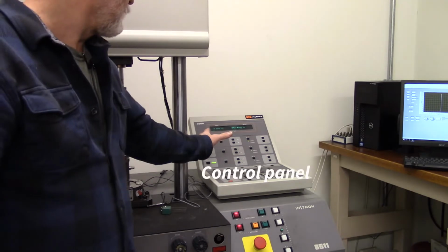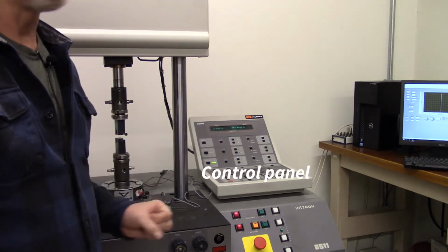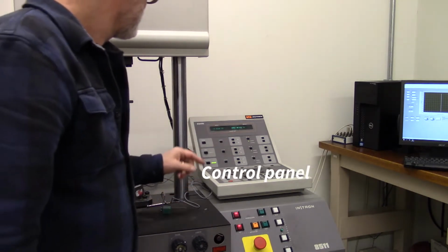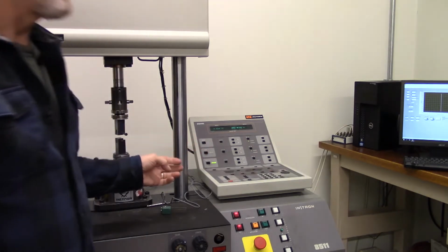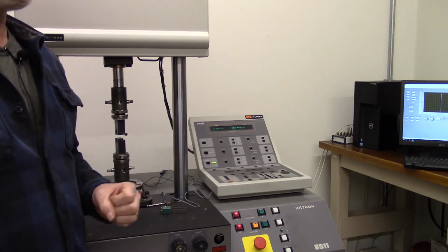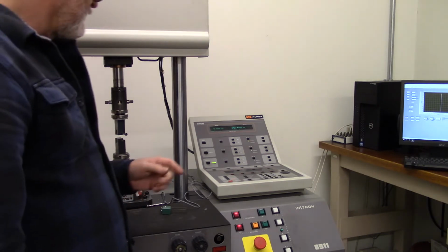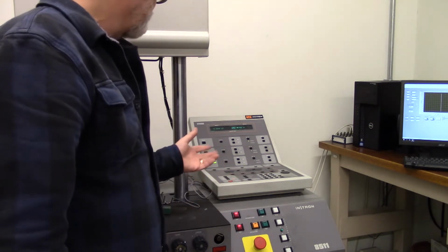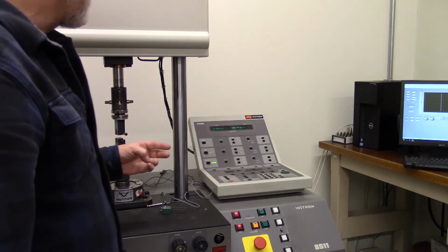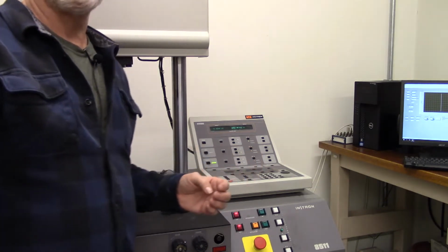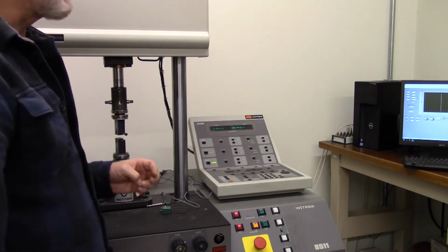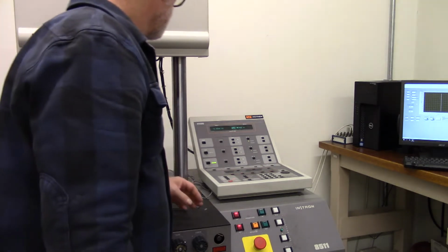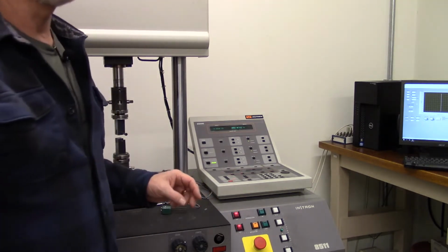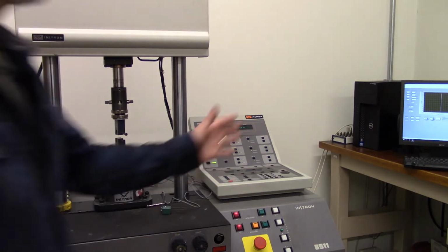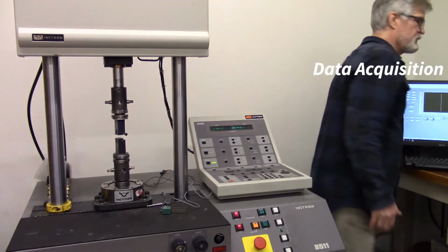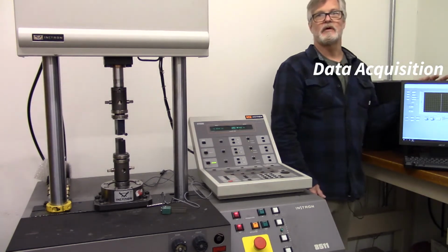Over here is the control panel where we program in our waveforms to control the actuator. We're going to be using a cyclic waveform for the pre-crack of the titanium specimen. And for the rest of the test, we'll use a ramping waveform to fracture the specimens. For the plastic specimens, we'll be using a ramp rate of 10 newtons per second. And for the titanium specimens, we'll be using a ramp rate of 80 newtons per second. Then over here, we have our data acquisition system, which will allow us to monitor and record the sensor inputs.